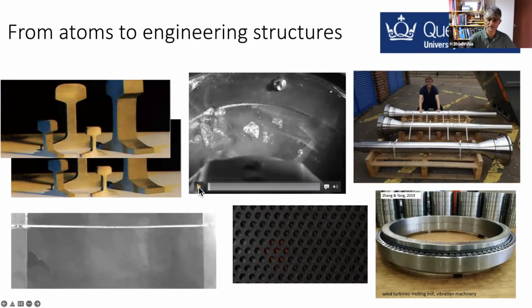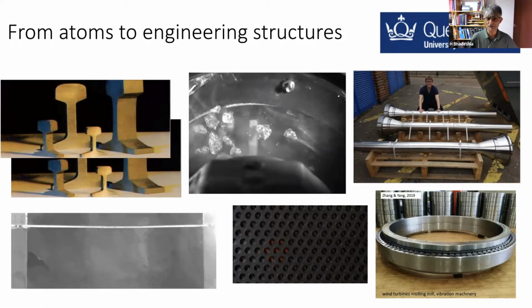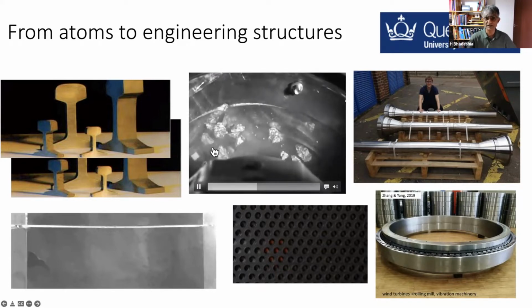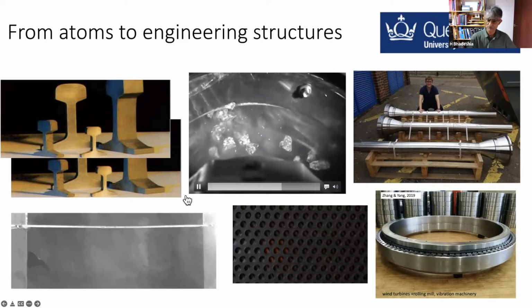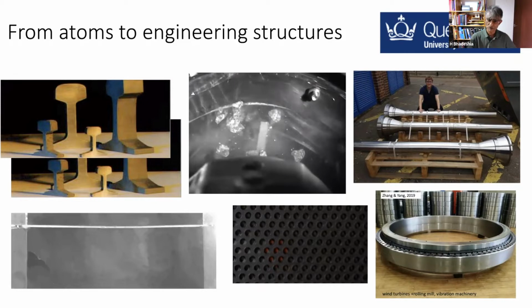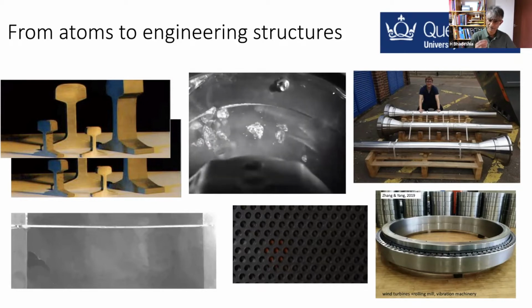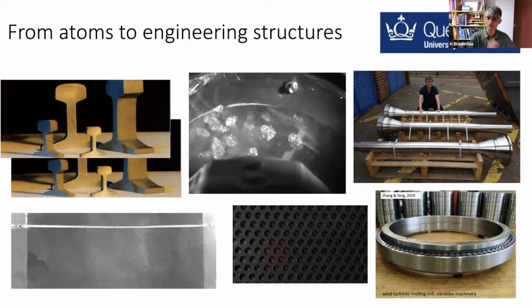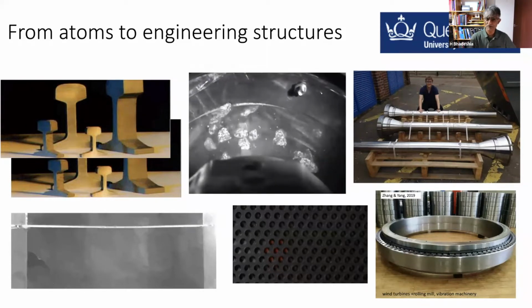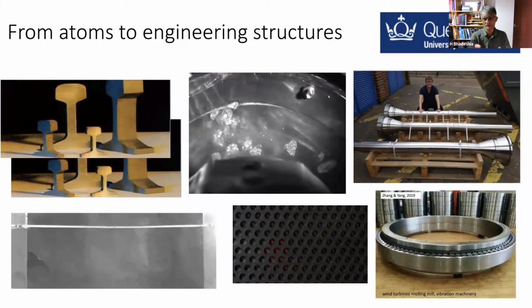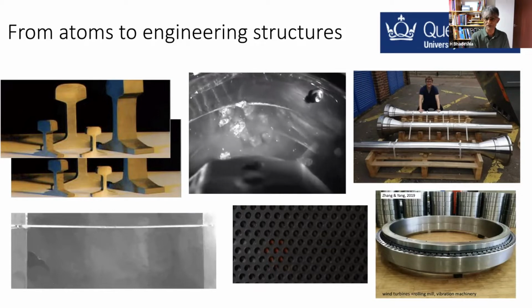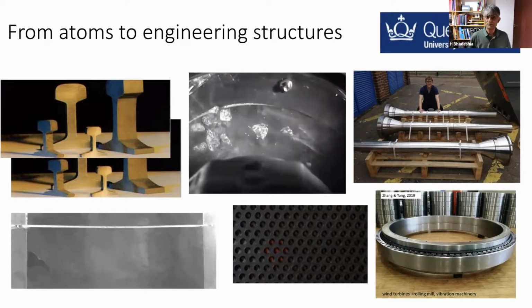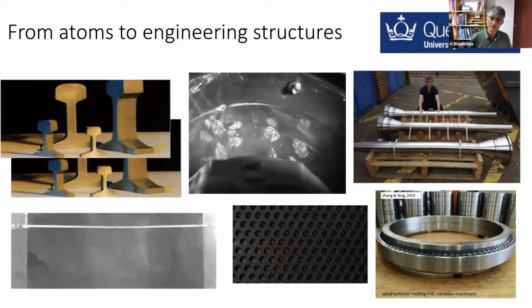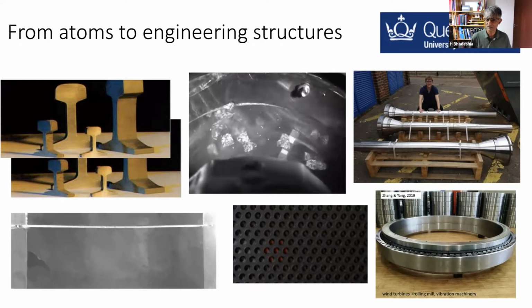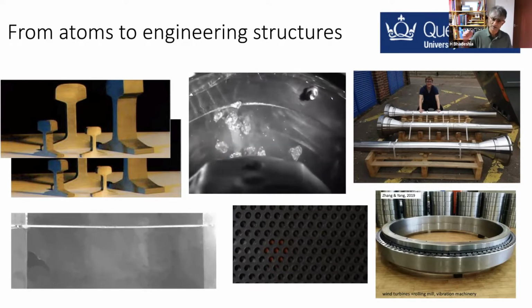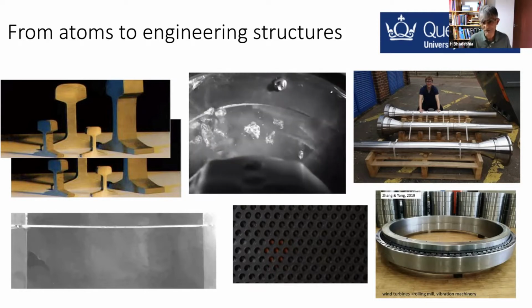So for example, this is a slow motion movie, slowed down by a factor of 300, and you see a steel sample that's hitting these granite particles because we've designed a new alloy which has effective grain size of about 0.4 micrometers, and by that I mean a crystallographic grain size. In other words, sometimes when you get textured materials, the actual size is bigger than what you see in a microscope. So the way in which we produce that is really interesting. This outperforms any commercially available material on impact abrasion. That means when you hit the material and you scratch it at the same time.